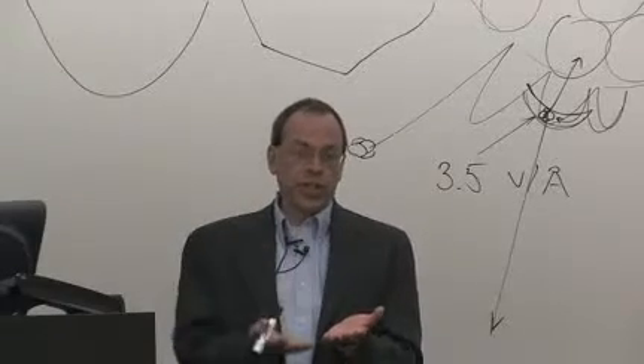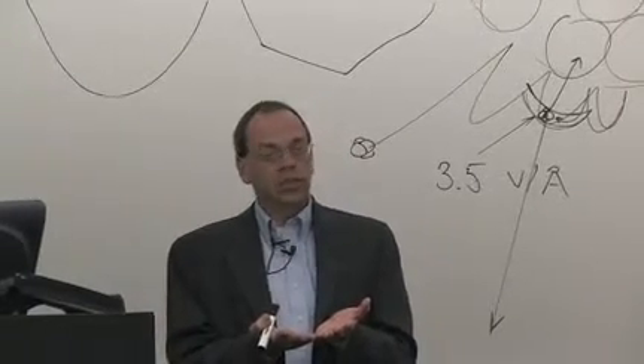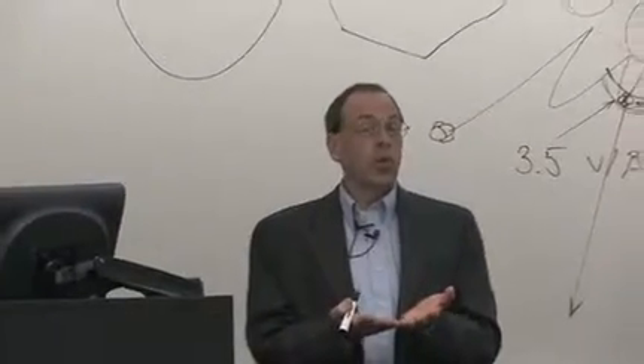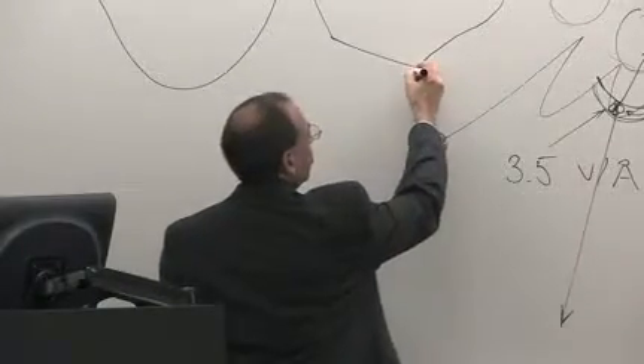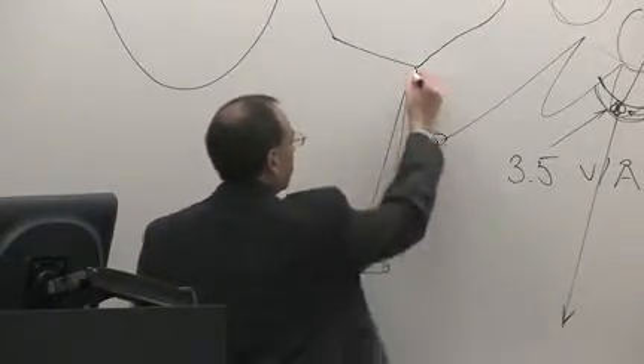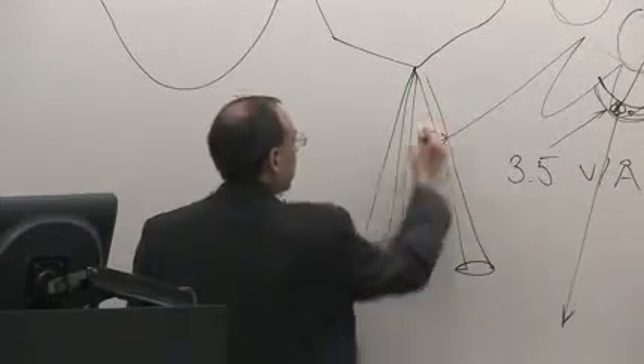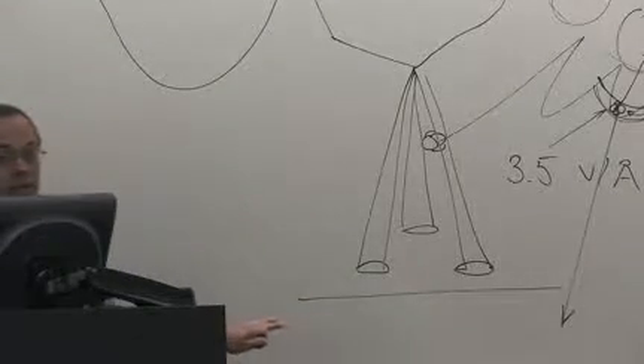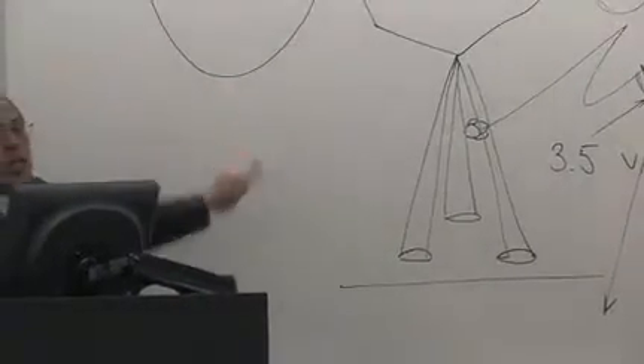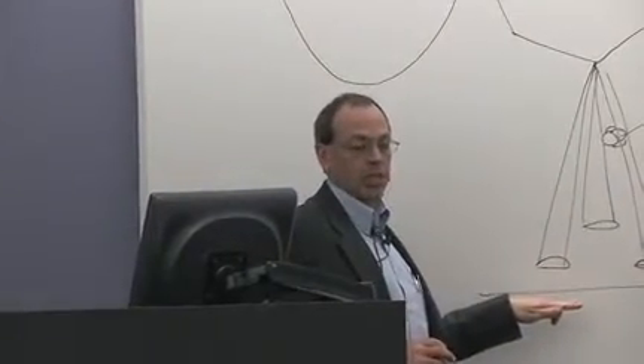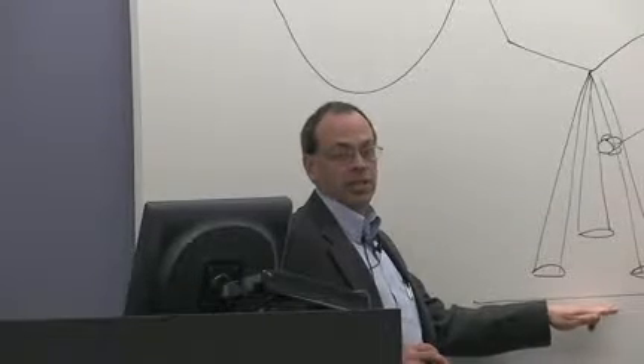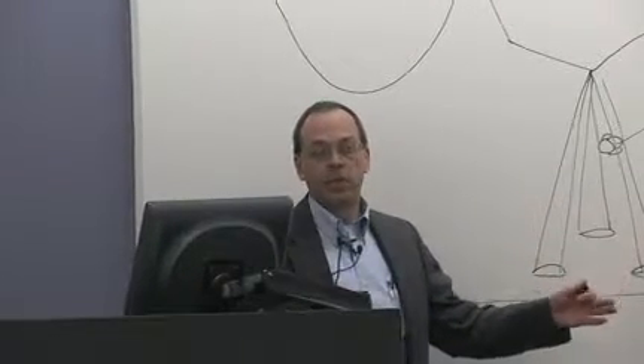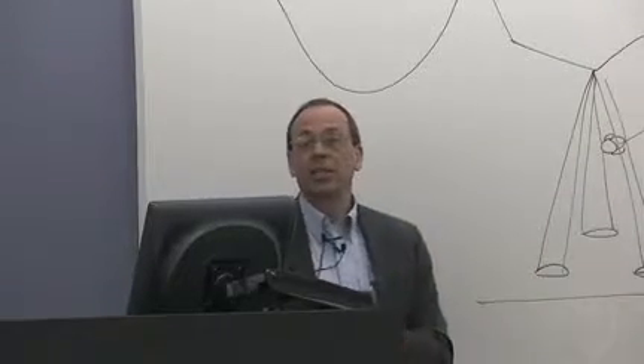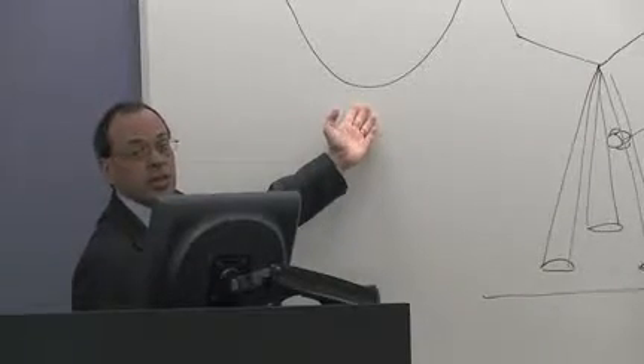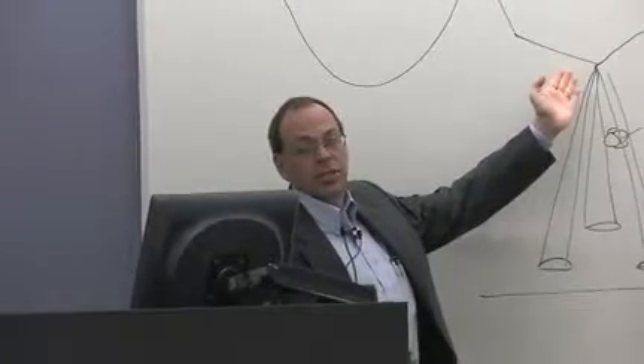If it was in a field ion microscope, you just look at that emission pattern hitting a phosphor. We've essentially built into our microscope a special mode where we can look at that whole imaging pattern. So, for example, if this is a well-built-up tip, you'll just see those 3 beams coming down, 1, 2, and there'll be another one here in the back. And you'll have that hit a screen, and you can look at that pattern. If it was in this shape, you'll see hundreds of little beamlets. So built into the microscope is a mode where you can examine the quality of the emitter. It's effectively like putting a screen here, seeing the pattern, and then you make a visual impression of, yep, I've still got my single atom at the apex. I'm going to keep on imaging. Or if you see hundreds and hundreds of atoms, you go through this process that takes half an hour to an hour. And then you're back with just 3 atoms at the tip.